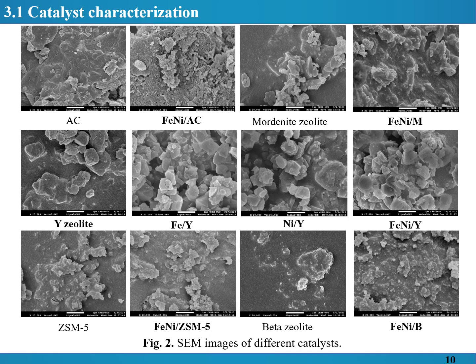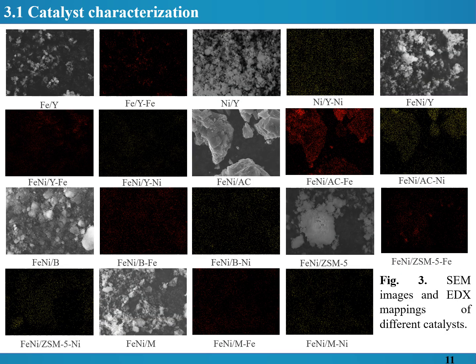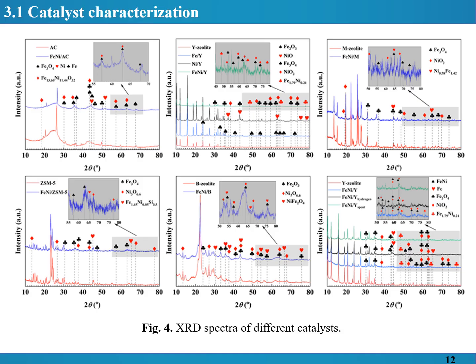The picture shows the SEM images of different catalysts. SEM images indicate that the introduction of Fe, Ni, or double dopant of Fe-Ni didn't lead to a significant alteration in the morphology of the catalysts. Figure 3 shows the SEM images and the EDX mappings of different catalysts. EDX mappings confirm the even dispersion of iron and nickel on both supports, including the different zeolites and activated carbon. This figure shows the XRD spectra of different catalysts, which confirms the formation of iron-nickel alloy in different catalyst supports.